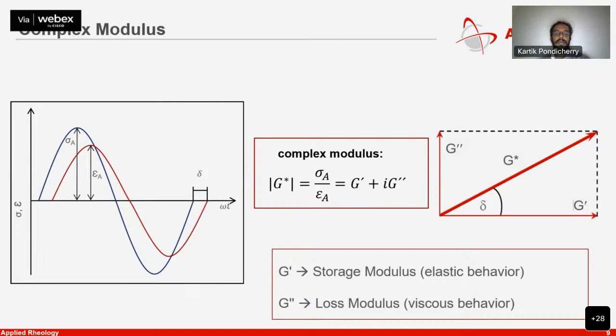But at the end, what you're looking at is if you're looking at it, then you're having stress and strain. And then how do you go from there over to something called as viscoelastic behavior and elastic behavior? So what you see here is you're applying a sinusoidal wave in an oscillation test where you have the stress that you apply and the resulting strain. And here you have the phase lag. So in case you are dealing with a perfectly elastic material, the phase lag is going to be zero or the phase shift angle is going to be zero. But if you have a viscoelastic material, then it's going to be anywhere between zero and 90 degrees. 90 degrees is for purely viscous materials. That will give you the complex modulus, stress amplitude over strain amplitude, which when you plot at an angle delta, which is this over here, then you get the X and Y intercepts as the storage and the loss moduli, which are actually going to give you the elastic and viscous behavior of the material. So this is the basis of what we do or how you can characterize different materials about the viscosity and viscoelasticity.